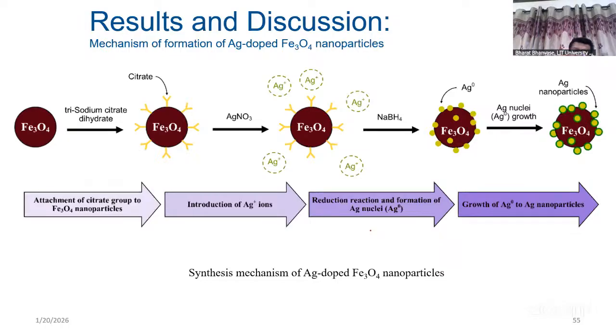So this is the mechanism of, we can say, Ag dope Fe3O4. First we have prepared Fe3O4 by using ultrasound assisted method. Then we have added some surfactant. That citrate surfactant is forming some functional group on these particles. And then Ag particles is coming and it is deposited here, right?